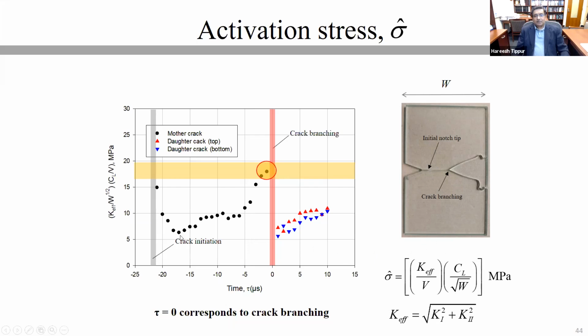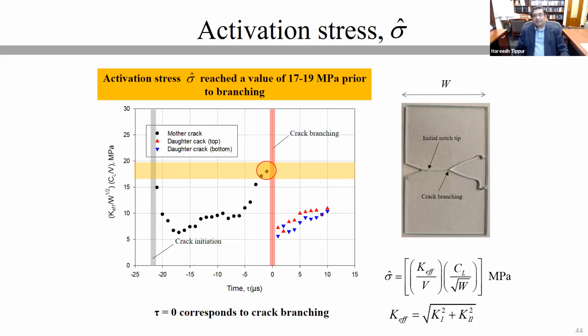What we observed by plotting the history of this activation stress, sigma hat, is that the branching occurred at a value somewhere around 17 to 19 megapascals. And then once the branching took place, the activation stress never reached a value high enough for it to branch again. So this was a hypothesis, and we tried to test this hypothesis with other experiments.